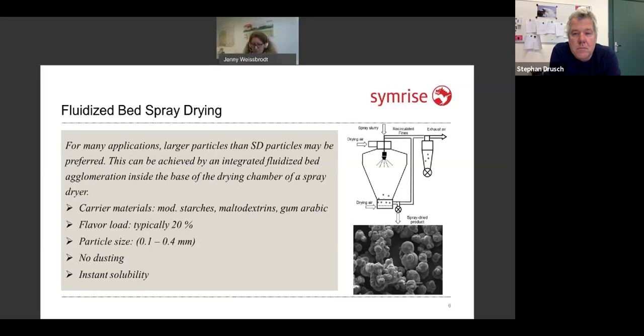So if you put these particles or these powders into a liquid, the particles will directly sink to the very bottom of your glass and then dissolve very easily. The particles here are around 100 to 400 microns. A flavor load in any kind of spraying process typically is 20%. Of course, it can go from 2 up to 50% load. We have no dusting in this process. This is why this process is used for many application fields where dust in the secondary processes has to be avoided. So it sounds quite easy, this whole spray drying process.